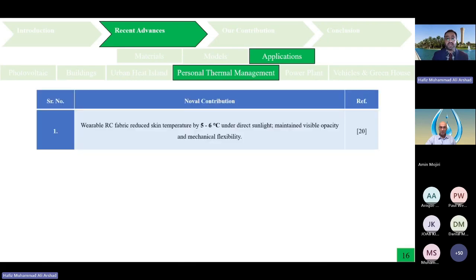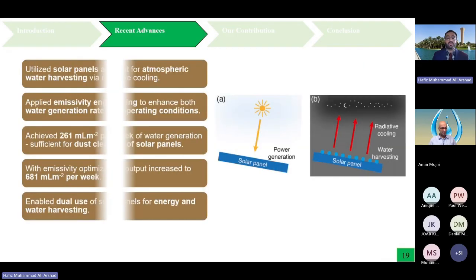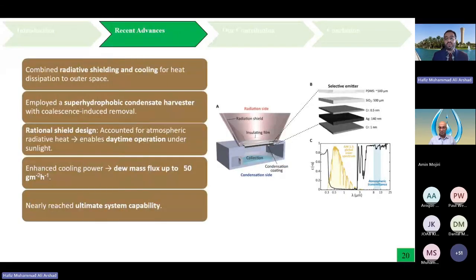Yes, actually, radiative cooling for air water harvesting is a really challenging field because humidity is one of the important parameters, as we know. But other than the humidity, the most important parameter is how we are going to avoid the thermal mass that is around. And if we have high humidity, then it is actually a resistance to the radiation. Even the radiation within the atmospheric window, where we have emissivity, once the humidity in the atmosphere goes high, it will ultimately be entrapping all of the radiation. So having a low relative humidity may promote